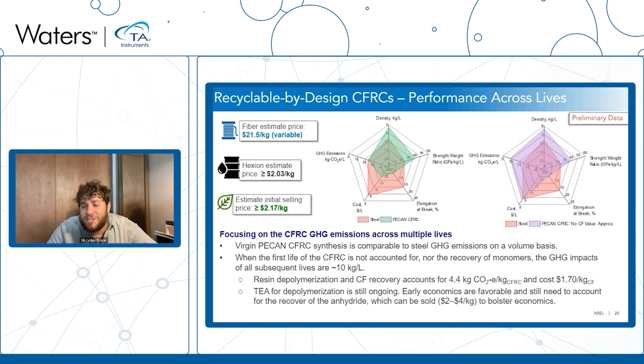When we depolymerize the resin and start using these materials for more than one life, you can actually have a material that is decarbonized relative to steel when you use it over 2+ lives, and the second life of the material actually ends up costing less than steel on a volumetric basis, which is really important because that's how we do our accounting.